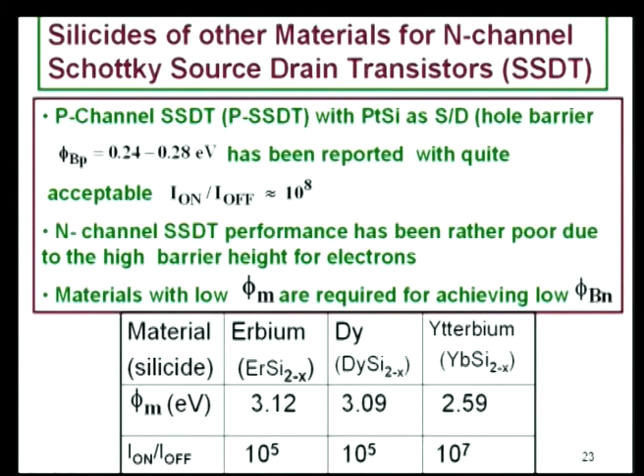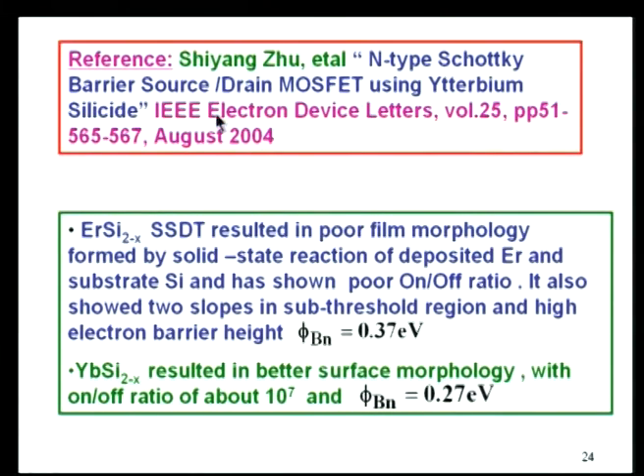But then, if you get low barrier height for holes, by the same token, you will say that barrier height for electrons is high. Very difficult to make n channel devices. Okay, we will get down to those things either in this lecture or when you go to germanium devices. So, here silicon was the case. Okay, they have erbium metal which has a low barrier height, and they got fairly good ion off ratios. Ytterbium gave much smaller barrier height. Okay. So, ytterbium was the one that they advocated for n channel; p channel no issue, p channel platinum silicide, n channel ytterbium silicide. So, those are the things which they have tried out, and ytterbium gave a barrier height of about 0.27, so some sort of acceptable devices were fabricated there. Of course, they had to make some passivation using forming gas annealing, etcetera, but not enough, should get better.